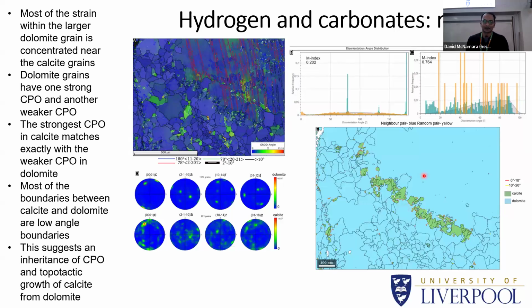This suggests that there is an inheritance of the crystallographic preferred orientation from dolomite to calcite, and basically that the calcite grew topotactically onto the dolomite and it's not precipitated by an external fluid.